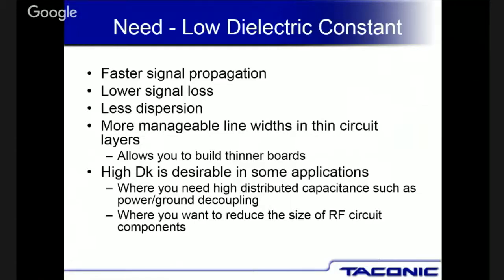And then by changing the dielectric constant of a board, you can change the size of the board. So for example, if you're doing something on FR4, which is epoxy glass, it's got a dielectric constant of about 4.5. Your traces may be, I'm going to say probably 25 mils wide. But if you want the same electrical performance, you could go to a dielectric constant of 10, and you can shrink the board down to half the size and get the same electrical performance. So a higher dielectric constant is desirable in some applications when you want to reduce the size of the circuit.